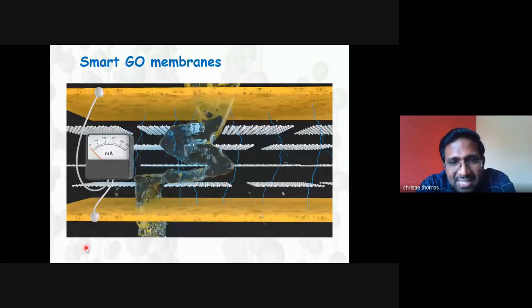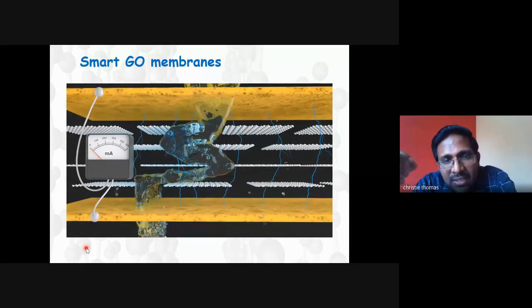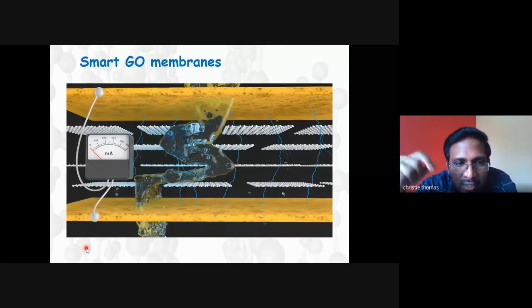I'm not going into details of this. In this schematic image, you can see a blue channel-like thing. Basically these are conductive filaments in graphene oxide membranes. We intentionally made conducting filaments in the graphene oxide membrane via controllable electric breakdown. Basically, if you apply an electric field across an insulator beyond a threshold voltage, electrically conducting channels are formed inside the insulator.